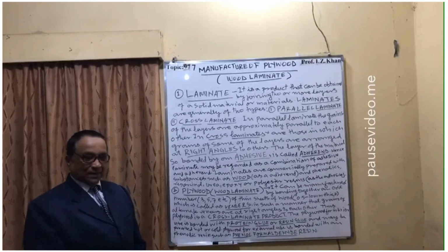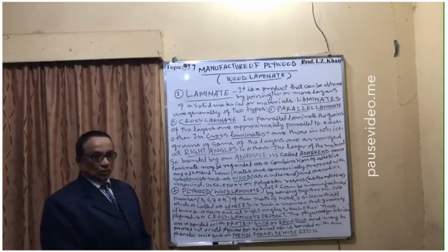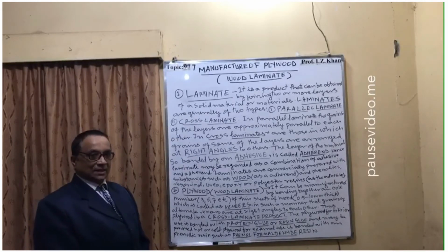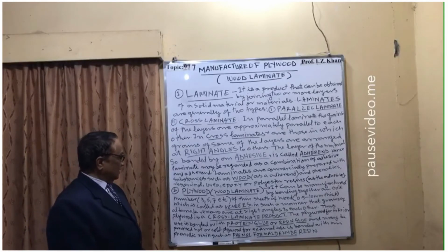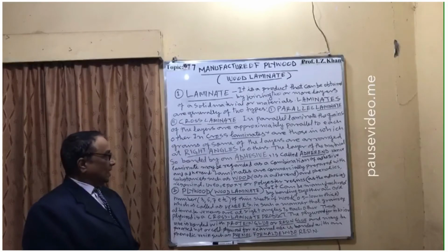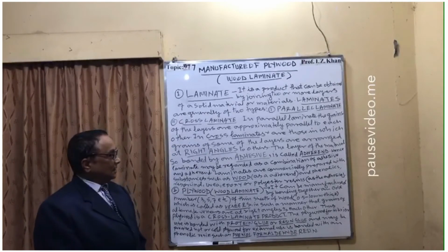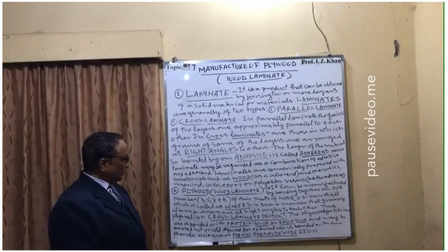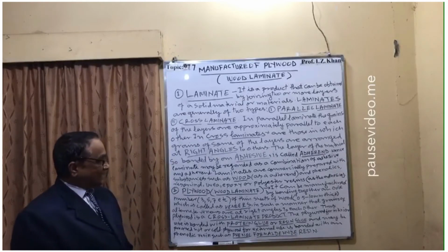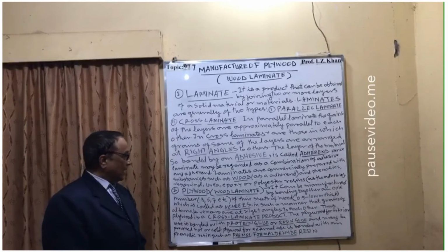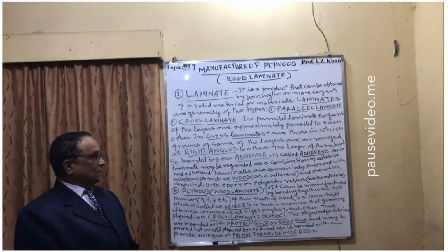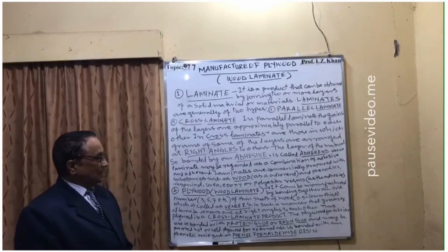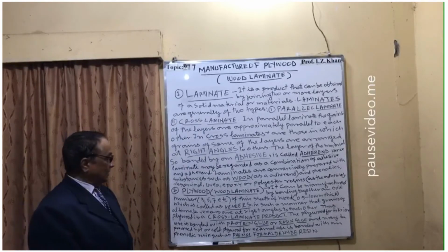Laminates are commercially prepared with substances such as wood. The very important material for plywood is the thin sheet of wood as the adherent, and phenolics, resorcinol, urea, epoxy or polyester resins as the adhesive. Number two, the manufacture of plywood or wood laminate. It can be manufactured by bonding together an odd number of wood sheets, either 3, 5 or 7 etc., of thin sheets of wood, and the thickness of the wood should be around 0.5 to 10 mm, which are generally called veneers.